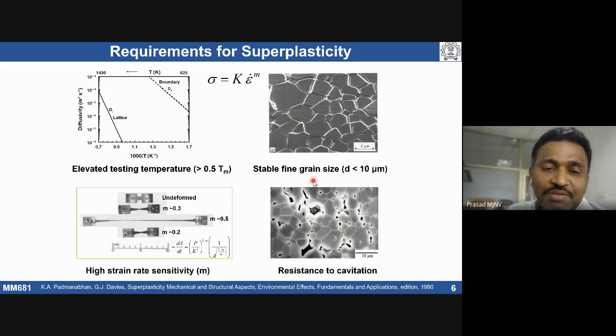The moment necking happens, non-uniform flow comes into the picture. The material is going to experience non-uniform flow, so it can fail at any point of time. If there is no necking, then we can get a very large uniform elongation. That is called flow localization. Necking is one of the flow localization phenomena, a plastic instability phenomenon. If we can postpone necking, that can lead to large uniform elongations.